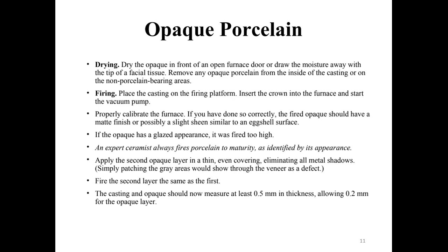Properly calibrate the furnace. If you have done so correctly, the fired opaque should have a matte finish, shouldn't be glossy, shouldn't be shiny, and more like a slight sheen or eggshell surface. If the opaque has a glazed appearance or it's shiny, that means the temperature that was used to bake the opaque porcelain was too high. And expert ceramists always fire the porcelain to maturity as identified by its appearance.